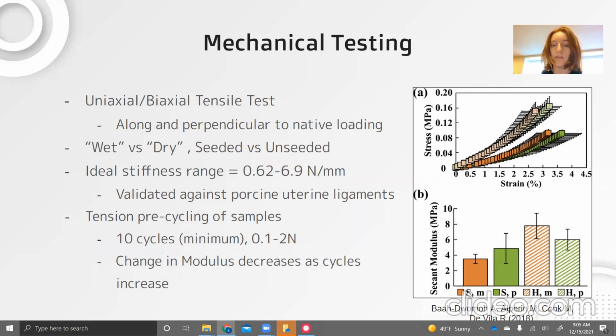And we would validate this against porcine uterine ligaments, which seem to have the same mechanical properties as the human uterosacral ligament. During these tests, we would also pre-cycle it with tension along the native loading direction with a minimum of 10 cycles ranging from 0.1 to 2 newtons. And this is because the change in modulus, the secant modulus specifically, decreases as the cycling increases. So at the beginning, there's a large increase and that sort of tapers off.